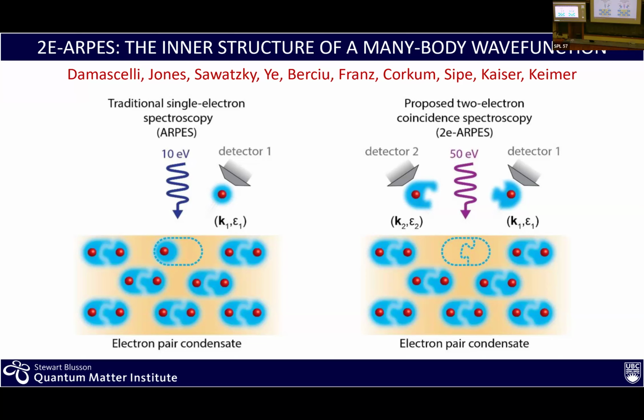And so the dream would be to come in with an energetic enough photon so that you could remove both electrons and then measure them at 2 detectors simultaneously in coincidence. And what you should expect is, if the Cooper pair has a total momentum of 0, the 2 electrons should come out with a plus and minus k, so opposite angles. So the idea is to go around with 2 detectors and collect the coincidence signal and really look at the angular structure of that signal and eventually look at the inner structure of that many body wave function. So really that's what we're trying to do. So this would be Cooper pair spectroscopy as opposed to single particle or single electron spectroscopy.